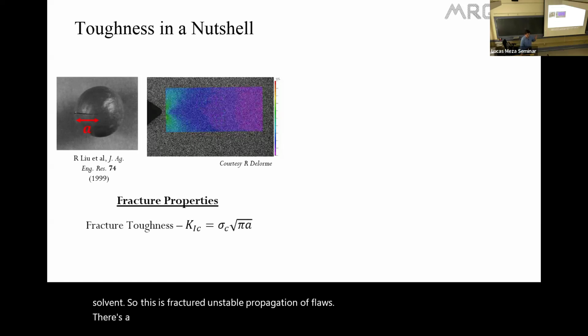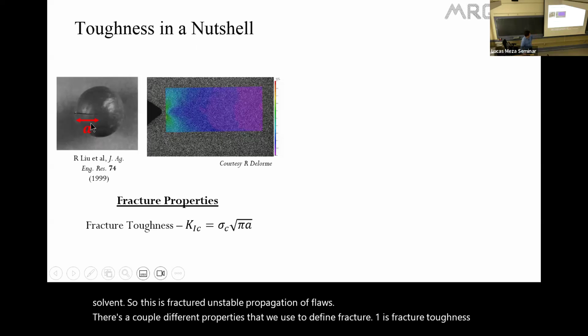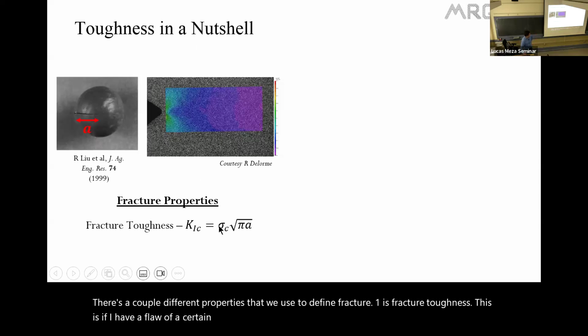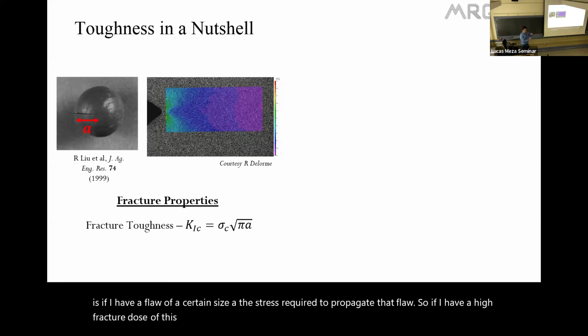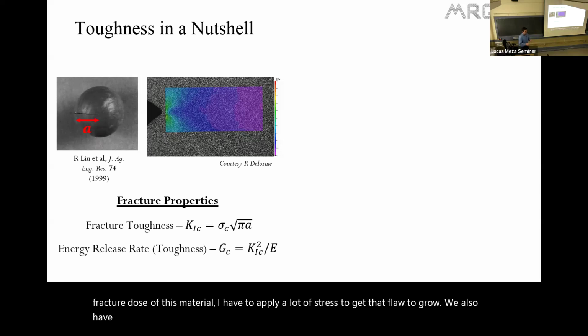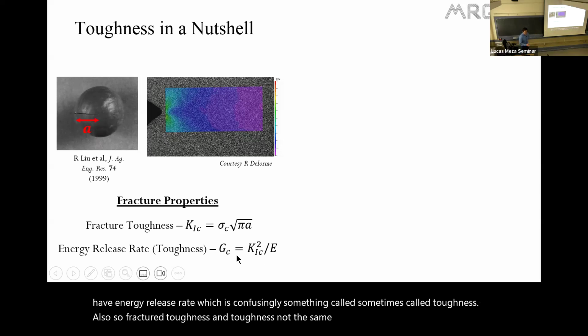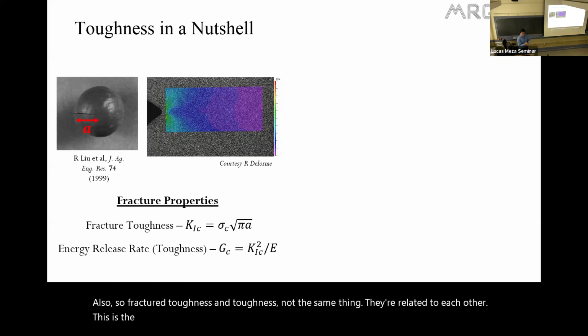There's a couple different properties that we use to define fracture. One is fracture toughness. This is if I have a flaw of a certain size A, the stress required to propagate that flaw. So if I have a high fracture toughness material, I have to apply a lot of stress to get that flaw to grow. We also have energy release rate, which is confusingly sometimes called toughness also. So fracture toughness and toughness, not the same thing. They're related to each other. This is the energy that it takes to propagate a flaw. So one is the stress, one is the energy.